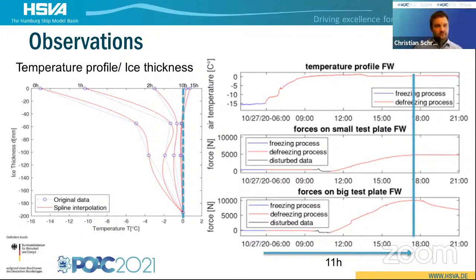Correct. We measured full scale quite high stresses, 200 kilopascal in floating sea ice. But of course, there are different time scales. There's one time scale in the heat penetration, and there's one time scale in the relaxation of the ice. And these two time scales, in a way, compete. In addition to Alexei's point about this, it's three-dimensional features.